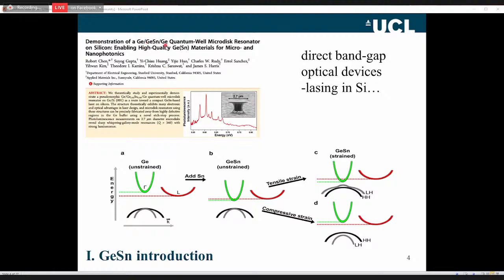Barrier materials are germanium, so it's a germanium-tin quantum well with germanium barrier material, and they've done some optical measurements. This is a photoluminescence plot from this structure here. The little disc there is germanium-tin, and the little bit that's been etched away is the germanium layer. The rough area at the bottom is the silicon substrate. We grow these on silicon, but there's a great selectivity in the etch. We can make these nanostructures.